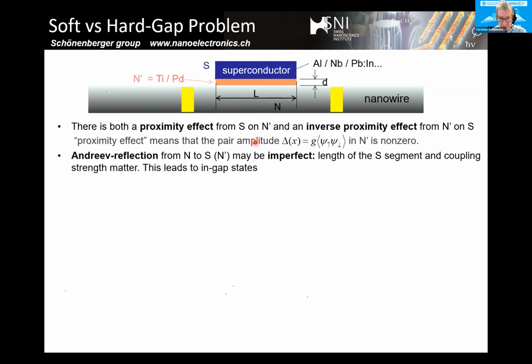And then you want to induce superconductivity in the bottom part. And there are many issues which can happen here. As mentioned, the interface could be not good. Maybe this palladium layer is too thick, the inverse proximity effect is strong, and this will actually lead to poor Andreev reflection at this interface in the nanowire, and that may produce a soft gap in the system.